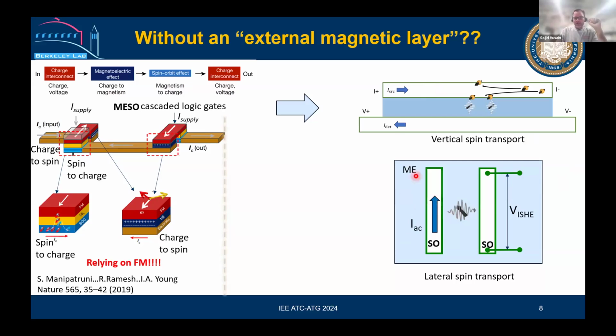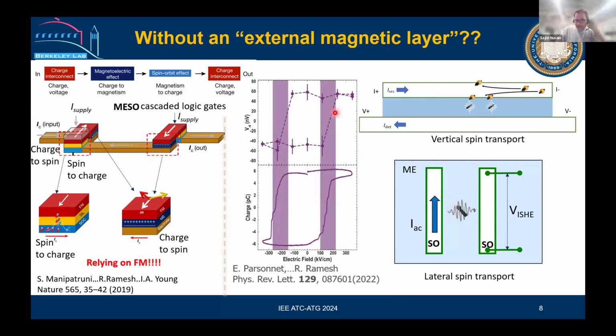So this is a bismuth ferrite magnetoelectric material, and we put some SO electrode on top of it. This is our first demonstration from years back by my colleague: this is the electrical hysteresis, and it's exactly overlapping the hysteresis measured as a function of electric field in this device, the open circuit voltage. Open circuit voltage means whatever you're measuring here is the influence of the magnetoelectric material and the spin Hall effect. So basically you are exciting the magnons in bismuth ferrite, and you're measuring the voltage output as an open circuit voltage. So it's following exactly the polar order.